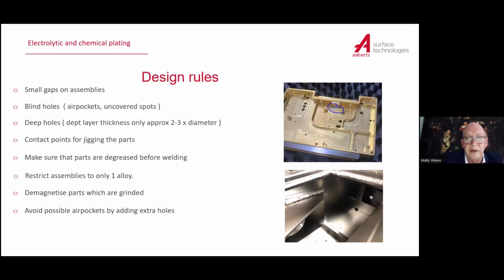Parts with coated areas: avoid those air pockets by adding extra holes, just as I meant. And what I meant is when you see those blind holes, on the right picture you see a very good example. The part is plated with gold, but due to the fact that oil is coming out of those holes, you get uncovered spots.